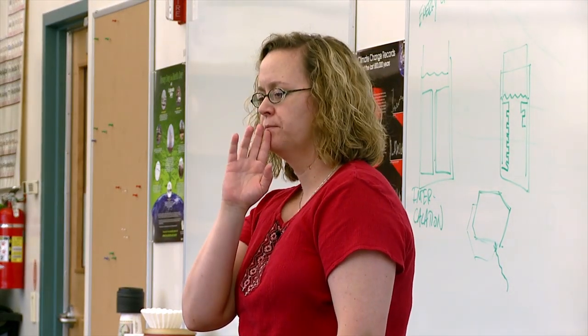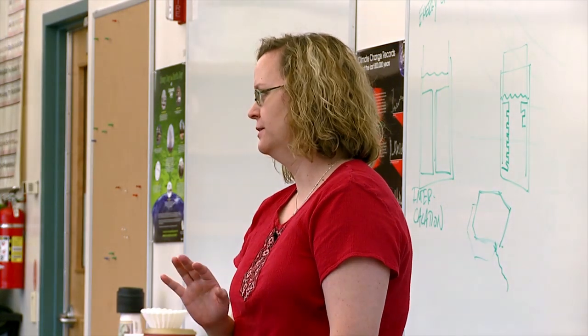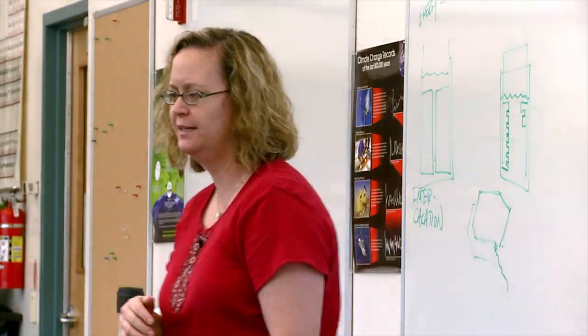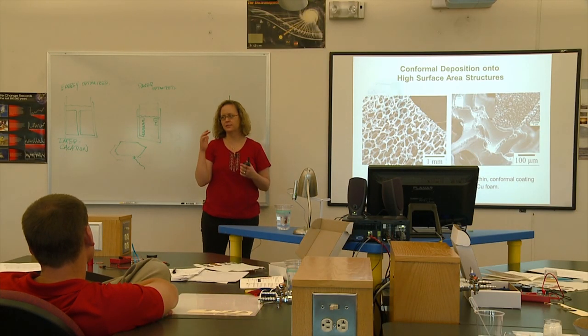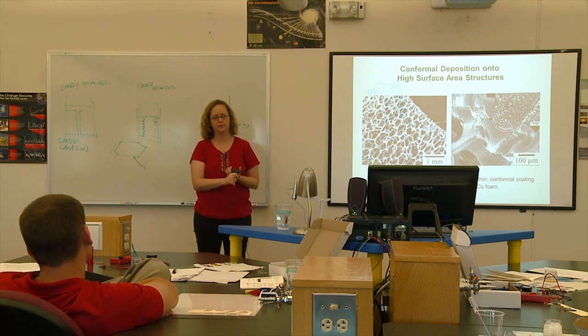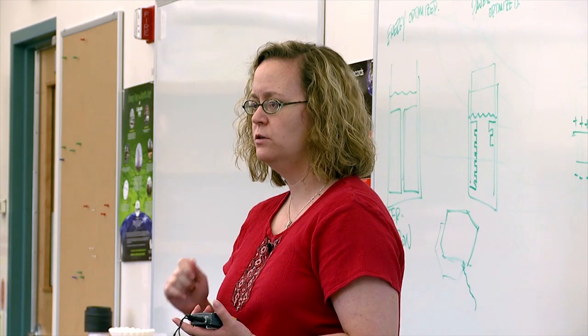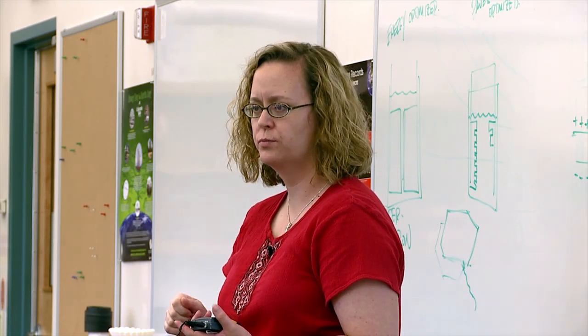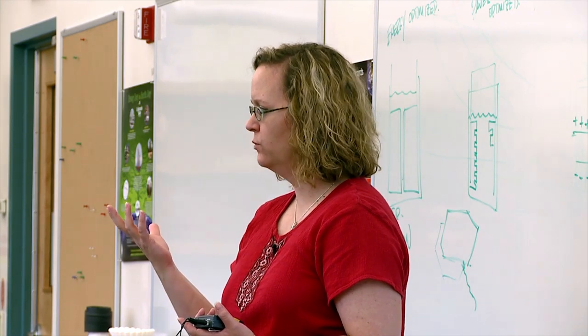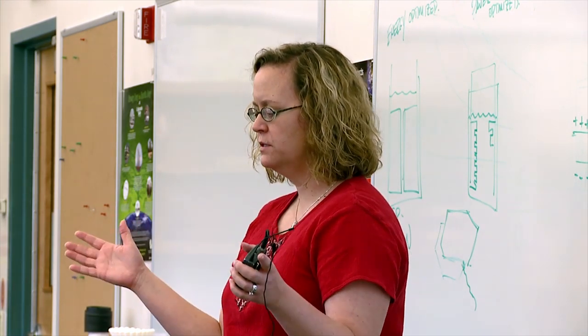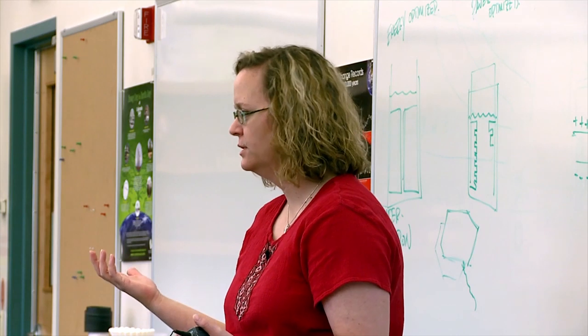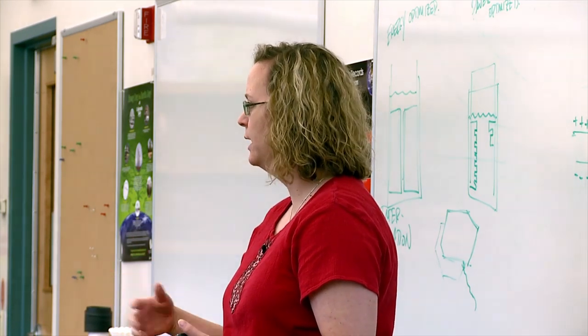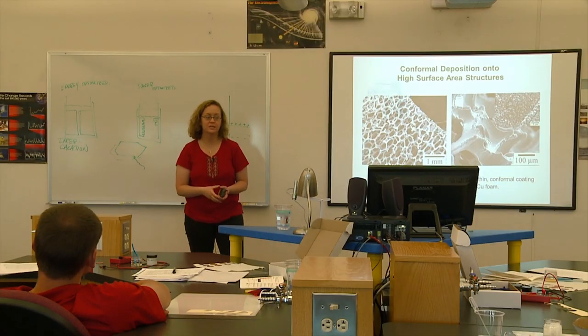Now this part, my very first PhD student figured out, and I gave him this list that fortunately he just didn't know enough to know shouldn't have been possible. The list was, okay, you have to figure out how to electroplate this compound, and that had never been done. And it has to be out of water, and it has to be at room temperature, and you can't use anything toxic. So what he figured out was that he could do it, but only if he used citric acid, which is a really common food preservative. It's a special molecule that will bind to the two metals, shifts their electrochemistry basically right on top of each other. It does it in this really special way, and it is literally something you can eat a lot of, and it's so cheap. You can buy it for $10 per kilogram. And so he's the one who actually made this happen.